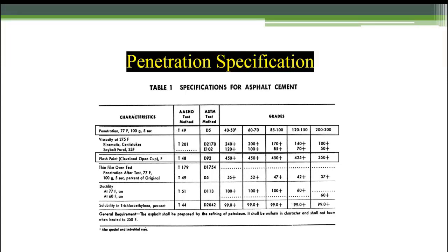So the 200, 300 is about 100 degrees lower. And after that, there was a thin film oven test and then a ductility test on that residual. And then when you're looking at purity, the bottom line there was solubility, and trichloroethylene is just a quality test, the test for contaminants. You can see that. So basic takeaway here is really penetration graded.